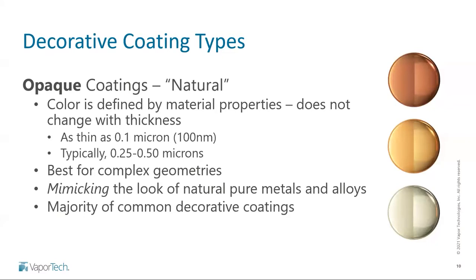And again, like I mentioned, these coatings are generally mimicking the look of pure metals and alloys. For example, we can match the color of things like gold. We may not be able to make them look exactly like gold, but it's a good representation, and generally, unless you're comparing them side by side, you're not really going to notice a difference. Some metals we can match almost exactly, stainless steels, nickels, brasses, for example, but some of the materials like coppers and golds are really, really difficult to get an exact match. And a lot of that has to do with the electronic structure and the conductivity of those materials that you just can't match with any other materials. And really, these are the majority of our decorative coatings.